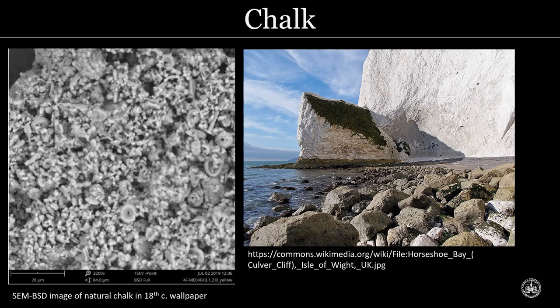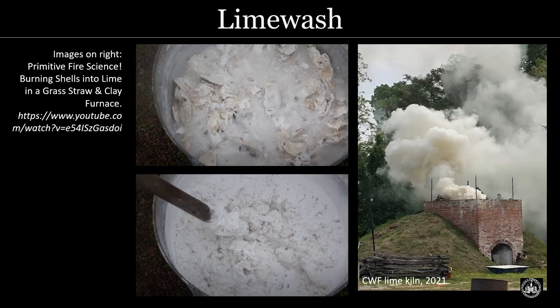So lime washes are another form of calcium carbonate that we see very often in architecture. So to make lime wash, lime can be prepared by calcining limestone or oyster shells. It's simple chemistry, but it's really like magic if you see it occur. I took these still images from a really excellent YouTube video about making lime from oyster shells, and here is the point where they're slaking the lime after calcining it with water to form calcium hydroxide. And it's just really, really amazing to see how they add water and these oyster shells just start bubbling and eventually turn to this white, limey slush that can be lime wash.